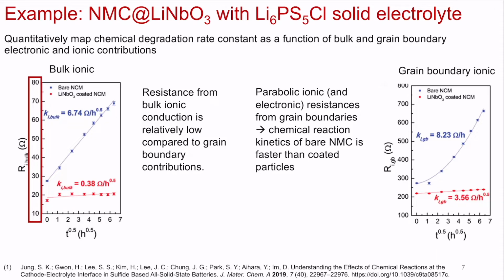Yeah. And so with the oxides, when we went through the list of possible decomposition products, the binary oxides tend to be stable, the fluorides as well. But when you start dealing with the sulfide compounds, those are extremely dynamic. And also, once you have the binary sulfides, the mechanical properties actually allow the material to sort of spread out a little bit more and have more contact, and thus now you have a larger surface area of reactivity to produce like H2S and other decomposition products that can be accelerated.